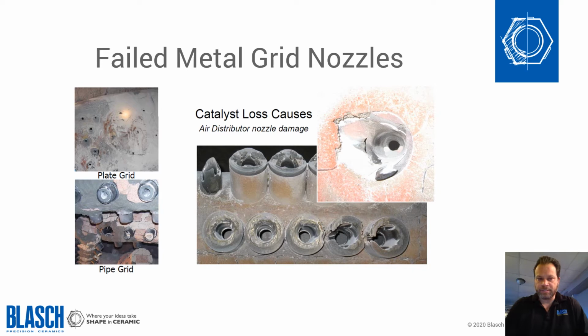Often what happens is one nozzle will start to abrade, and the flow path of the air coming out will cause a unique situation where it starts to impinge upon its neighboring nozzle, the pipe itself, or even the refractory that surrounds it. Once that starts happening, it's almost like a domino effect, in that the nozzle next to it starts to wear away, and that in turn causes the next one to start to wear away.